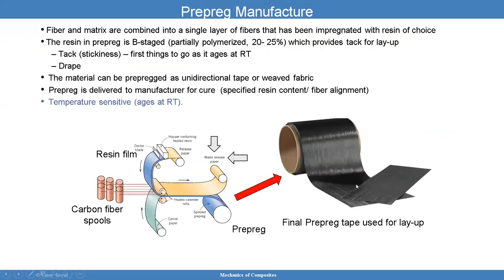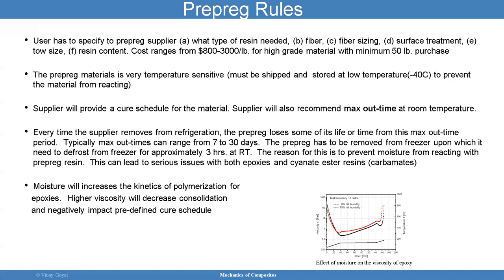The prepreg has to be removed from the freezer, upon which you then need to defrost it. Of course, if I want to be able to use this material, I cannot use it frozen. I have to let it thaw, kind of like when you buy a frozen cake and you need to heat it up, it's the same process. You have to leave it outside until it comes back to room temperature. Typically 3 hours should be good enough. And the reason for needing that, particularly to take that step, is that you don't want to have moisture reacting with a prepreg resin. And why you're going to have moisture is because you have condensation. And so if you take something that's really, really cold and you heat it up, it's going to have condensation. So it's better for things to kind of defrost at room temperature, and then you can take over.